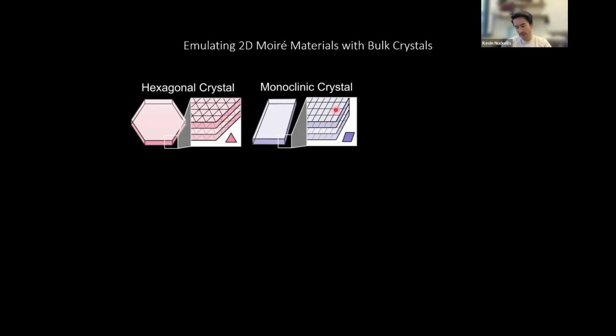I'll remind you that in this layer configuration, hexagonal and monoclinic crystals are actually very similar, but monoclinic crystals are a little less symmetric. In fact, monoclinic has one free angle. So this unit cell has an angle that is not something round like 120 degrees, but something random, like 105 degrees or 112 degrees, something not round. So these crystals, experimentally, would be identified by their symmetries in diffraction.